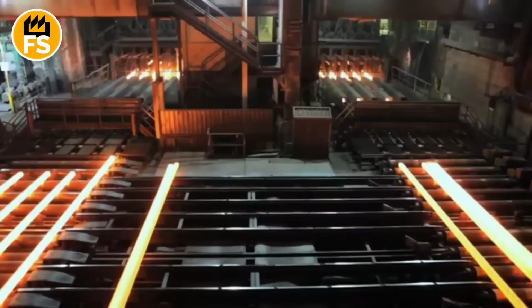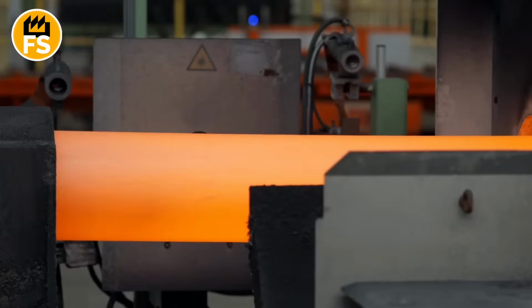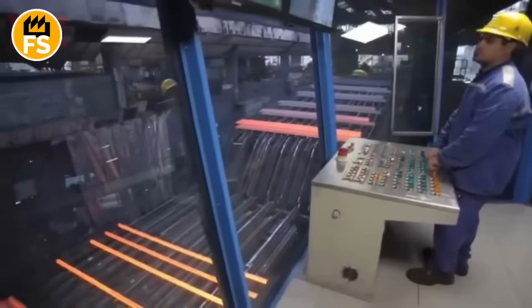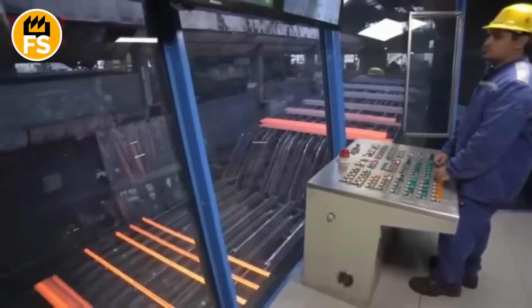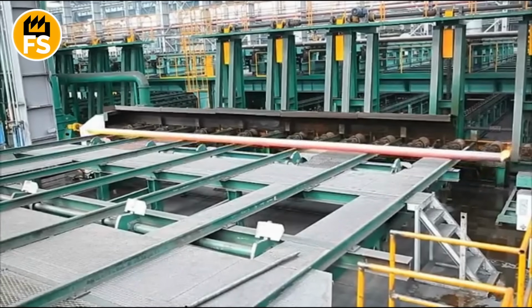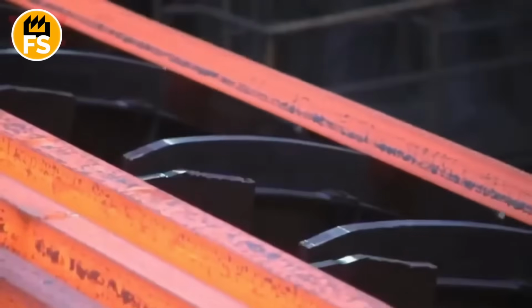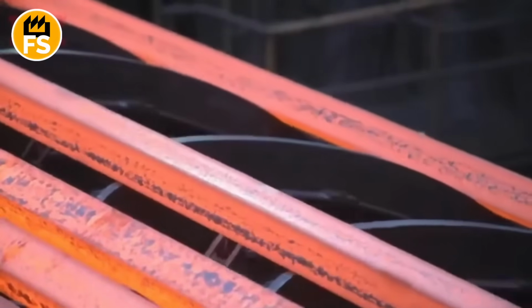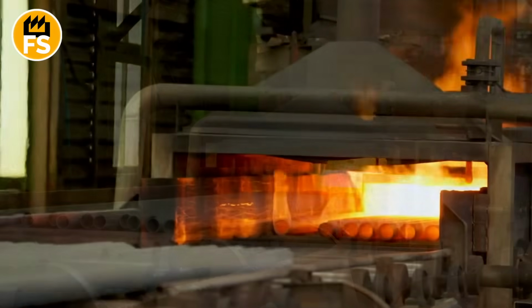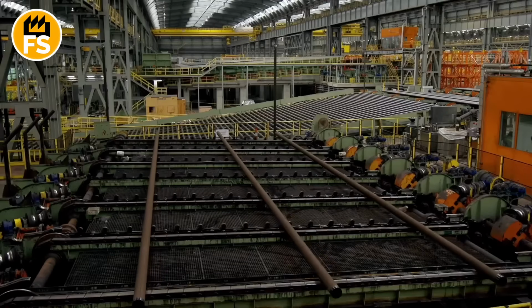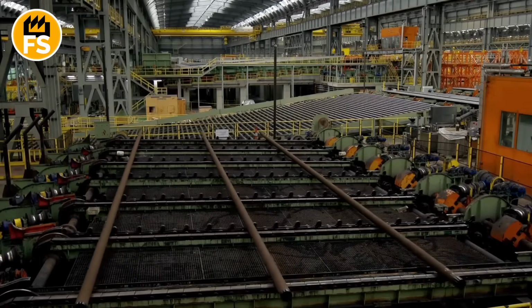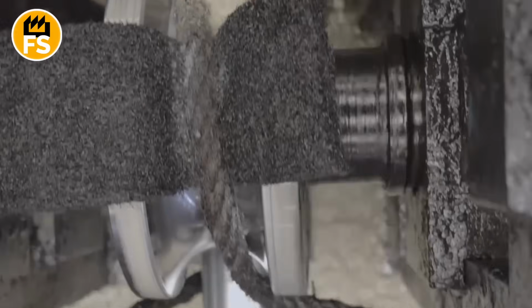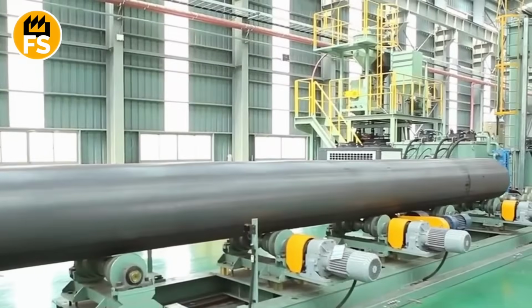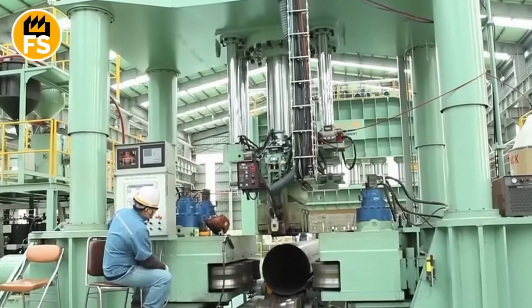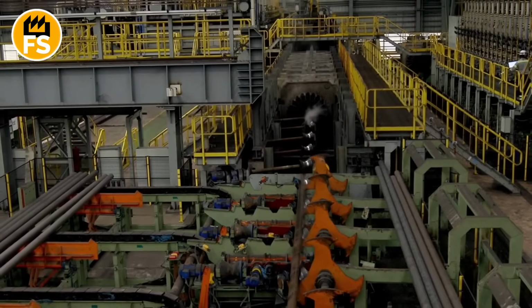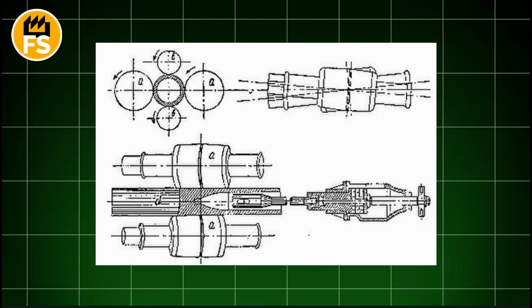At this moment, immense force is at work. The billet is rotated between 2 conical rolls, spinning in opposite directions. The rolls don't just squeeze the billet, they create strong rotational and axial pressure, causing the billet to stretch along its axis, flowing around the piercer point. To avoid cracks or ruptures, the pressure and temperature during piercing are controlled very carefully. If the billet cools too quickly, or the pressure is distributed unevenly, it can break or lose the required shape. Therefore, the process runs without interruption, and with strict adherence to all parameters. This process is called the Mannesmann method, named after the German engineers who invented it in 1885.